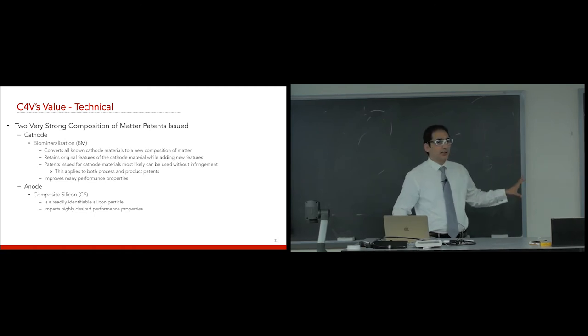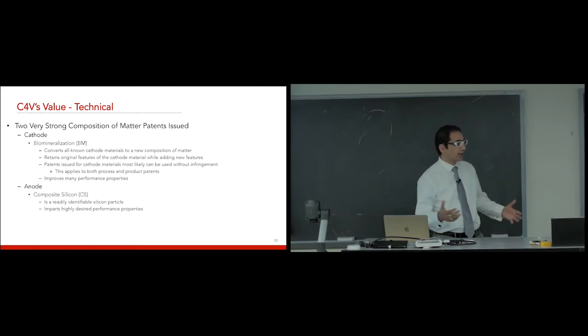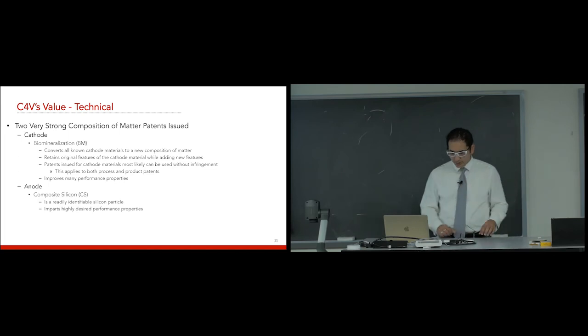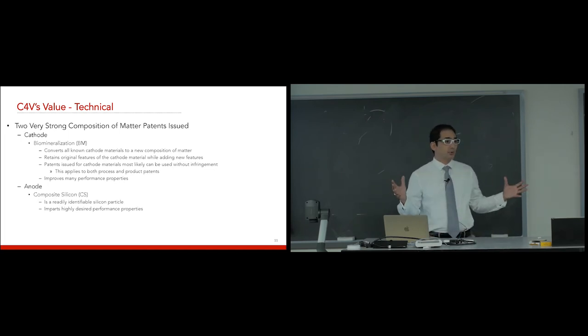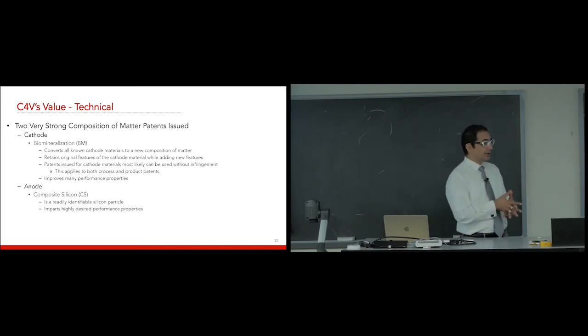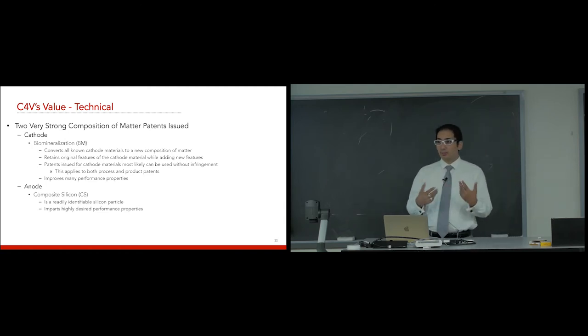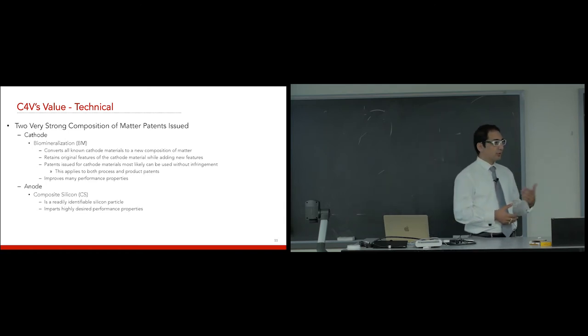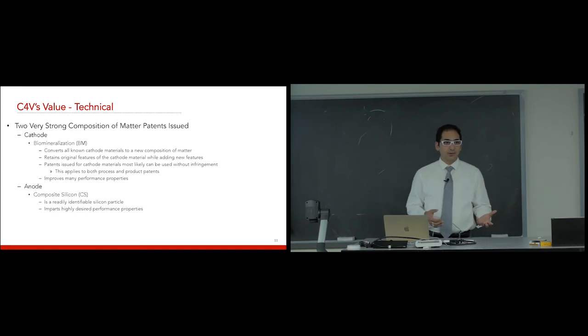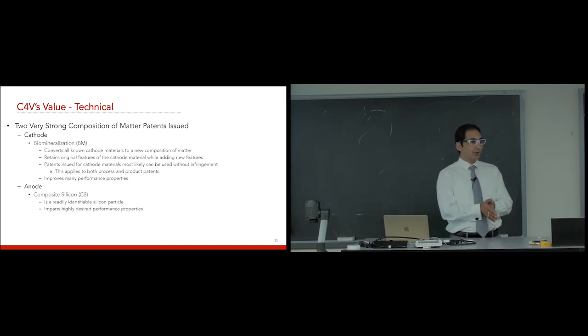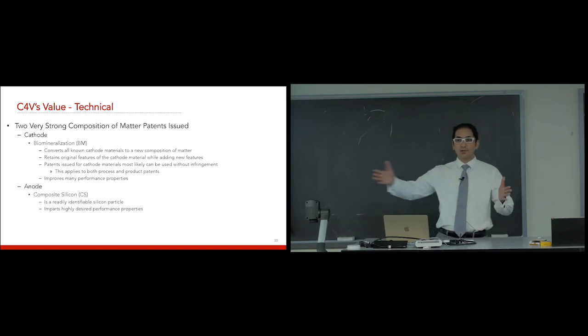Then we have composite silicon. Silicon, again, known for its high energy density. The challenge is it breaks as you make it react with lithium. And every time it breaks, it has to form a new surface. So every time a new surface is formed, you lose some lithium. So if silicon is used, although you can get higher capacity, you won't get good cycling because every time you lose the lithium.